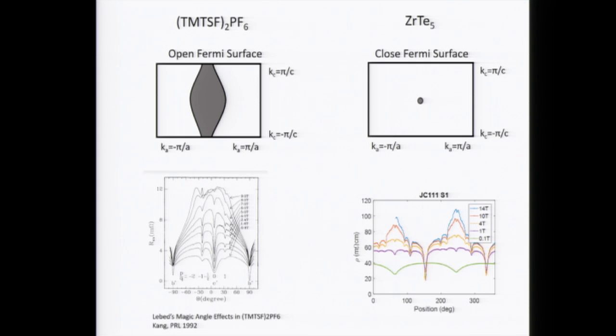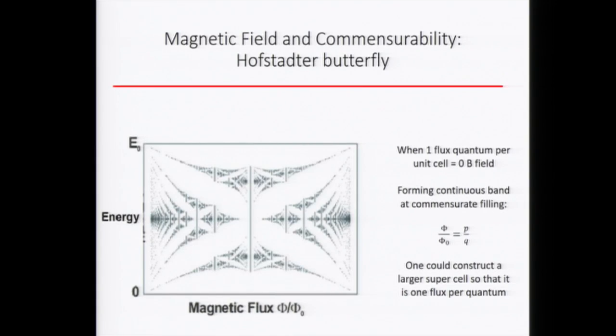So this definitely reminds you of the case of the Hofstadter butterfly of graphene in the boron nitride Moiré superlattice. So let's quickly review the essential ingredient of a Hofstadter butterfly. In this Hofstadter butterfly spectrum, you have the magnetic field, and this is the ratio of magnetic flux. When you tune the magnetic field, you see a repeated pattern when your magnetic flux is 1 flux quantum per unit cell. And then you have these discrete fractal spectrums as a function of energy and magnetic field. But there's some special magnetic field, when the flux to flux quantum ratio is a commensurate ratio, like P over Q, where P and Q are integers.